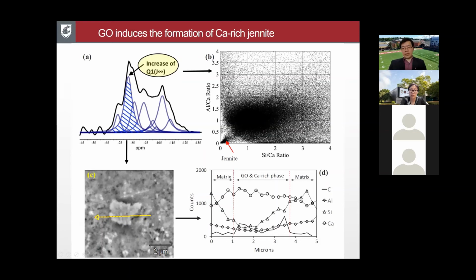But in general, again, the graphene oxide in those modified groups is only 0.02% by weight of binder. Now, because it's a pervious concrete, we don't use the fine sand. So you have designed porosity or permeability. So they look like this.